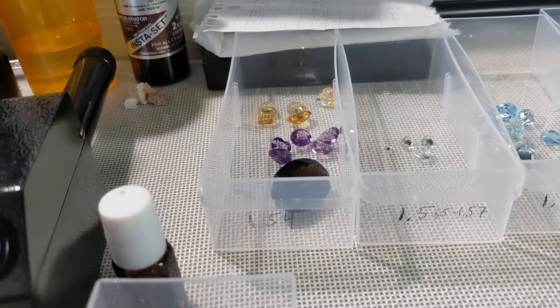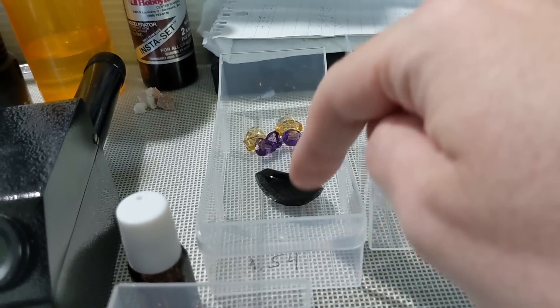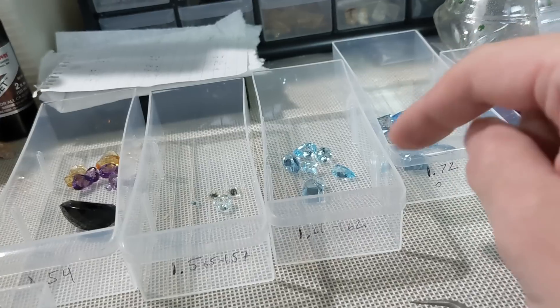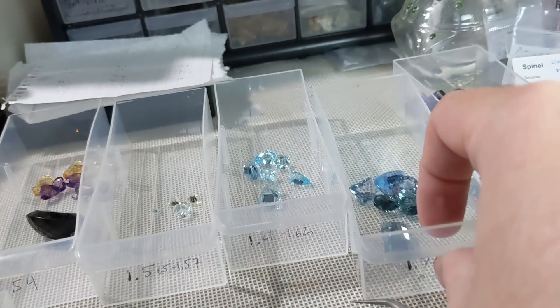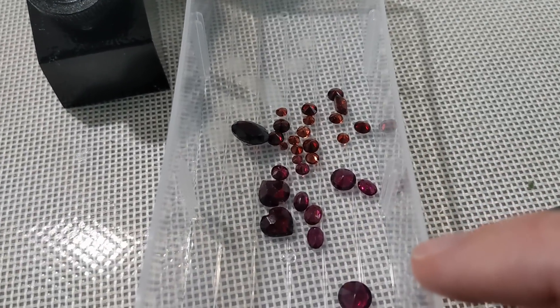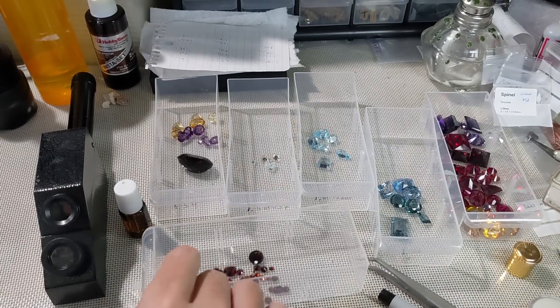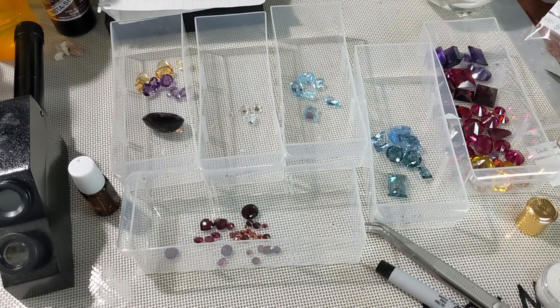In the end, I'm satisfied with the separations I made: quartz — which includes amethyst, citrine, and smokies — a couple of aquamarines, topaz which are natural but likely heat treated, spinel at 1.72 which is almost definitely synthetic, lots of synthetic sapphire based on size and clarity, and then those garnets. A refractometer and dichroscope are good indicator tools but are not wholly diagnostic by themselves and should be used with other identification methods and your common sense and experience. For me it was probably an overdue purchase, and I'm glad to have one now in my toolset.